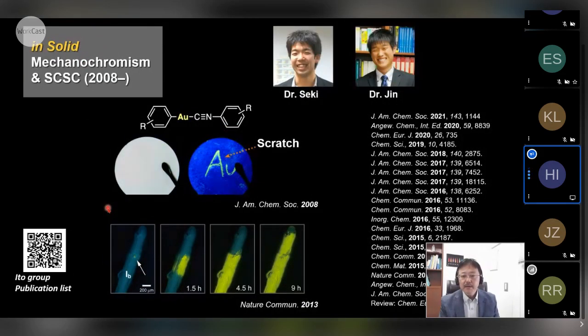The other part is mechanochromism and single crystal to single crystal transformation of gold isocyanide complexes. During our synthetic chemistry study, we found that a gold isocyanide complex can show very interesting mechanochromism, that is, an optical property response to mechanical stimulation of the solid material. For example, you can add mechanical stress on the surface of this compound, and you can see the color change of the luminescence. More recently we also found that small mechanical stimulation can induce single crystal to single crystal transformation all over the crystals. This is more sensitive to mechanical stress.